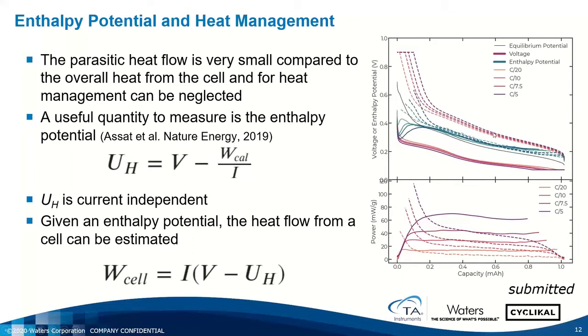Here in this cell, I have silicon being cycled at different rates. We can see that the potential window opens up as the rate goes higher. In this bottom panel, we have the power from the calorimeter. If I use the potential and the heat from the calorimeter, I can calculate the enthalpy potential, and we can see that both on charge and discharge at all currents, it lies on top of each other. So we have a constant enthalpy potential that's current independent.